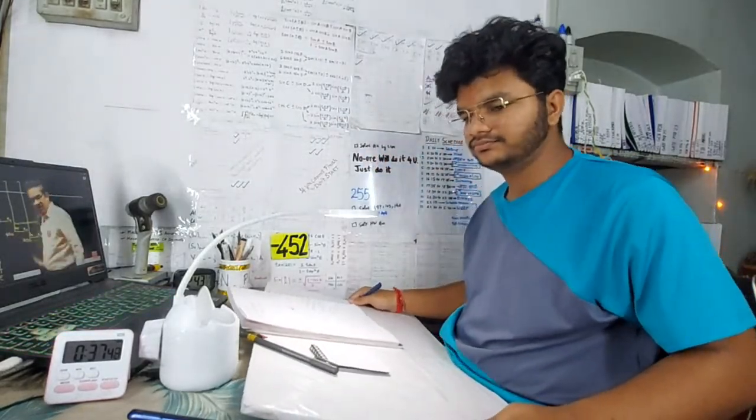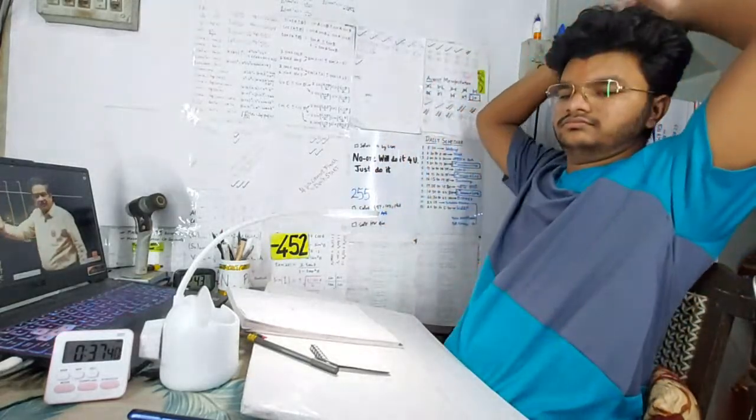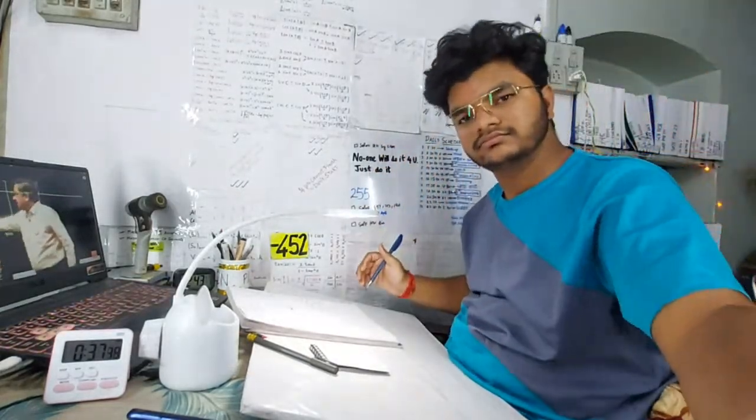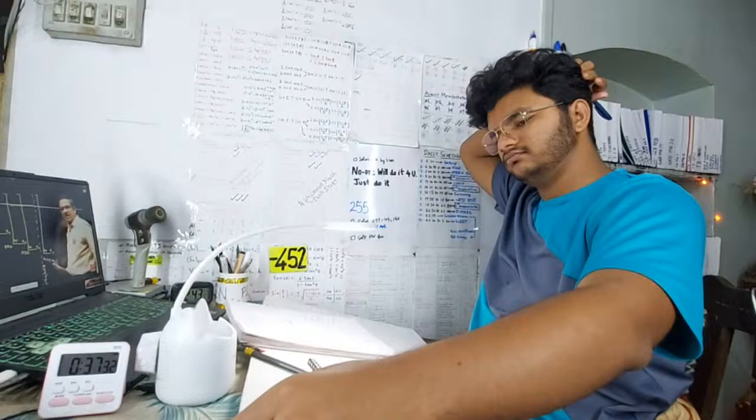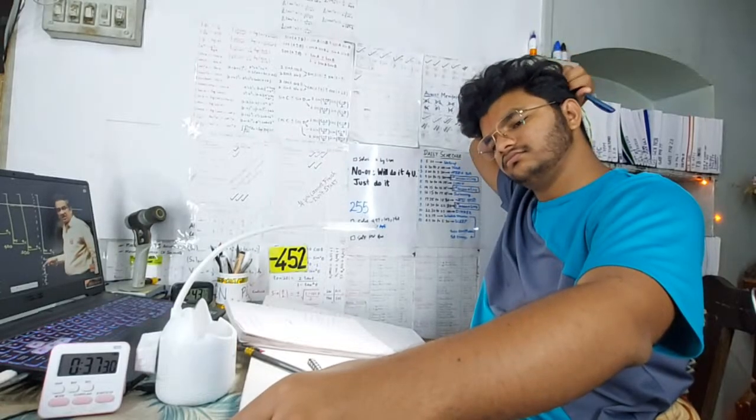Now, at different temperature ranges, the austenite transformation product will be different. Up to 550 degrees centigrade, austenite will transform into pearlite. Below 550 degrees centigrade, by constant temperature holding, austenite will transform into bainite. Below 210 degrees centigrade, austenite will start transforming into martensite.